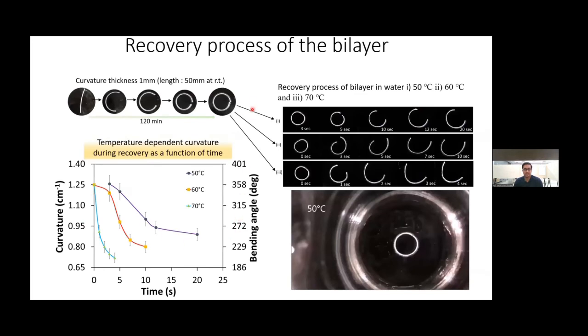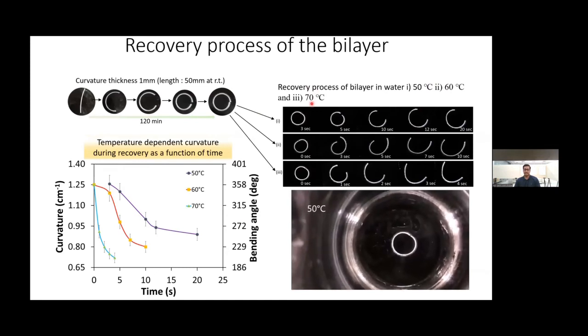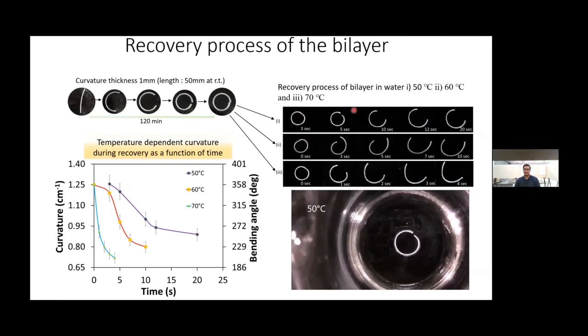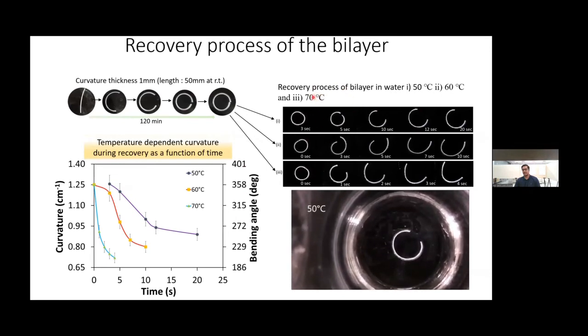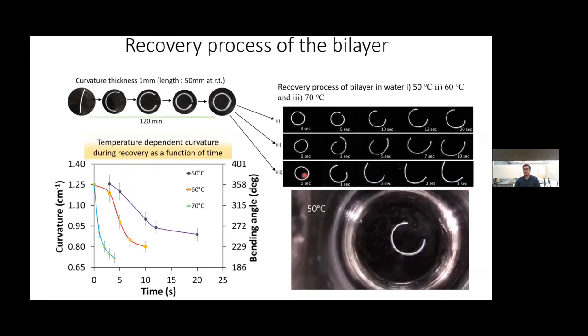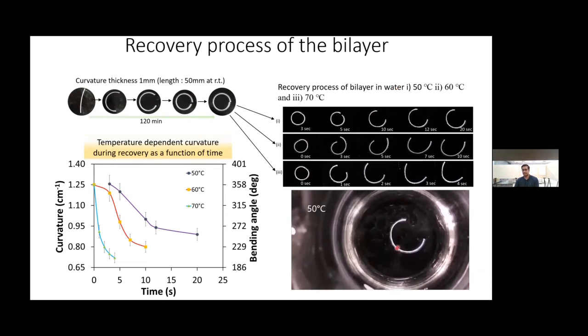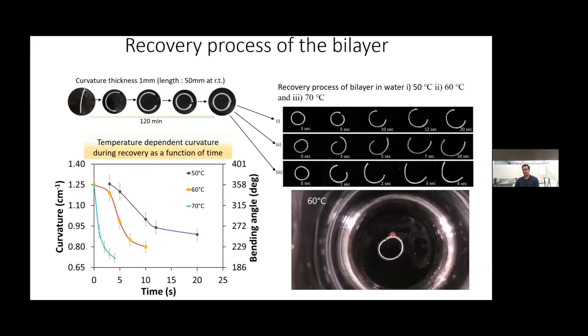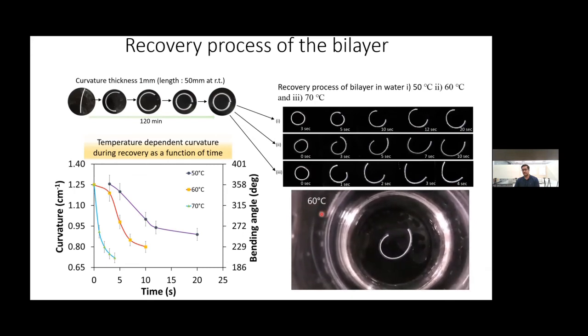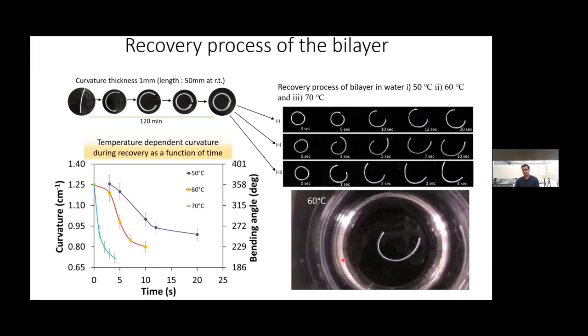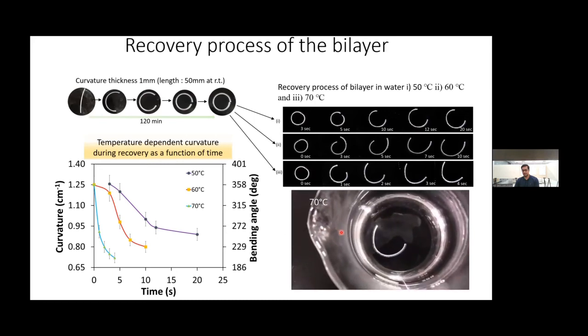This is the recovery process of the bilayer system, and in this process, I have used 50 degrees Celsius, 60 degrees Celsius, and 70 degrees Celsius. We have found that at higher temperature, like 70 degrees Celsius, the recovery process is faster than at 50 degrees Celsius and then 60 degrees Celsius. You can see in the video, this recovery is very slow at 50 degrees Celsius, but quite a bit faster at 60 degrees Celsius and even faster at 70 degrees Celsius. You can see this is much faster.